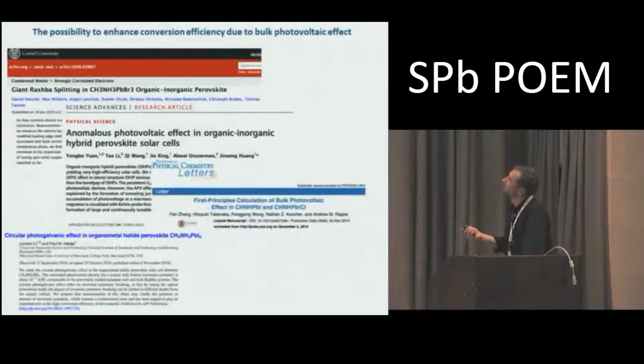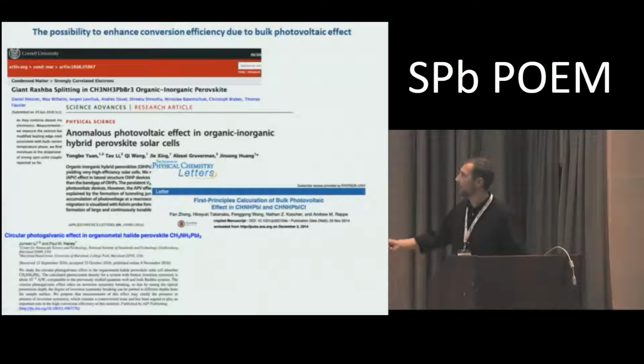During the last 2 or 3 years, many works were published, mainly theoretical works, on calculation of the bulk photovoltaic effect in this material. This effect could provide a way to enhance the efficiency and to obtain efficiency over the thermodynamic limit. One of the theoretical papers focused on calculation of the circular photogalvanic effect in MAPI samples, and they related it to symmetry breaking due to spin splitting in this material.